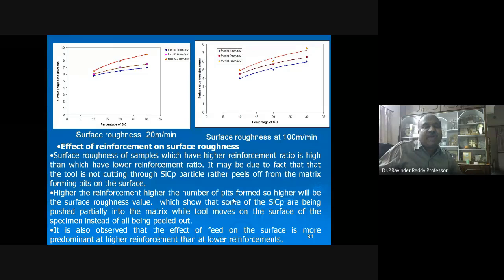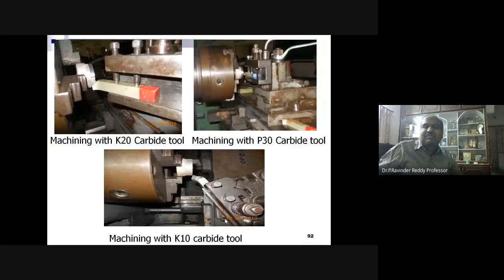It may be due to the fact that the tool is not cutting through the silicon carbide particulate, but rather peels it off from the matrix. The higher the reinforcement, the higher the number of pits formed, so the higher the surface roughness value. We show that some of the silicon carbide particles are being pushed partially into the matrix while the tool moves on the surface of the specimen, instead of all being peeled out. It is also observed that the effect of feed on the surface is more predominant at higher reinforcement.